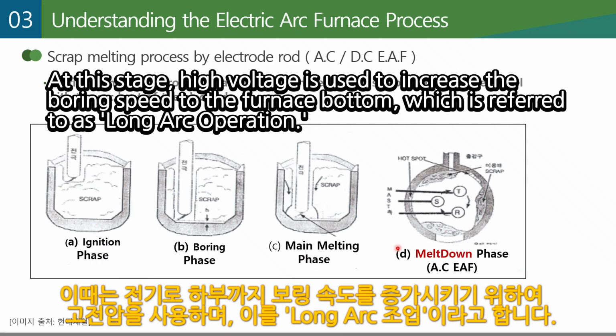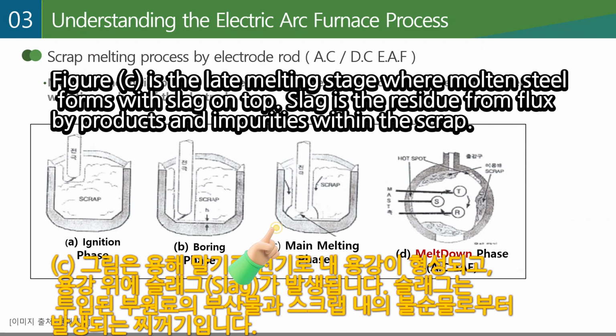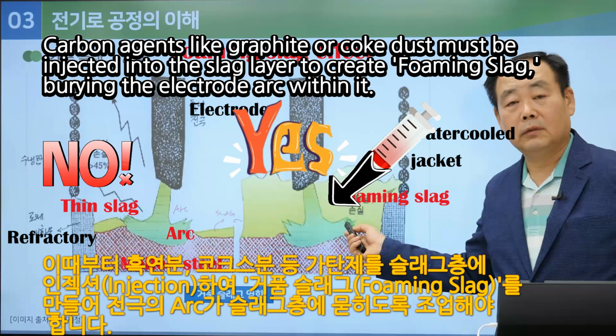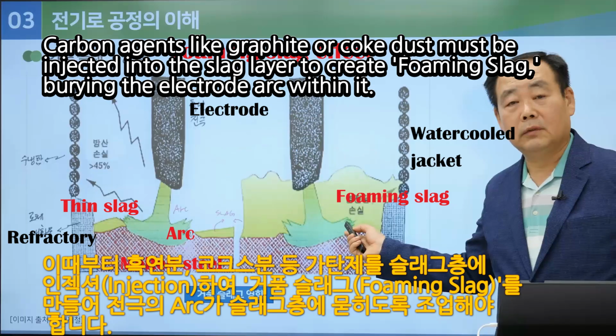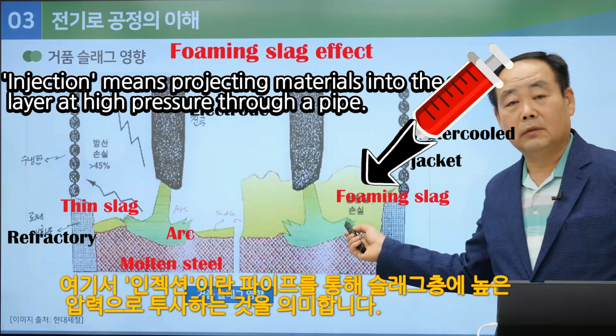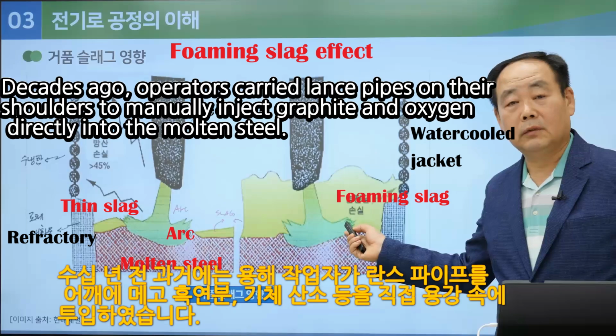At this stage, high voltage is used to increase the boring speed to the furnace bottom, which is referred to as long arc operation. Figure C is the late melting stage where molten steel forms with slag on top. Slag is the residue from flux, byproducts and impurities within the scrap. Carbon agents like graphite or coke dust must be injected into the slag layer to create foaming slag, burying the electrode arc within it. Injection means projecting materials into the slag layer at high pressure through a pipe.